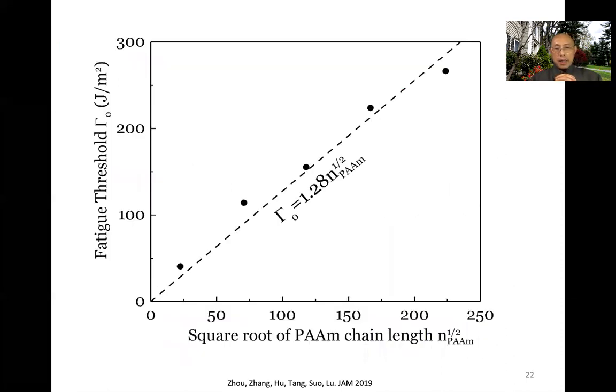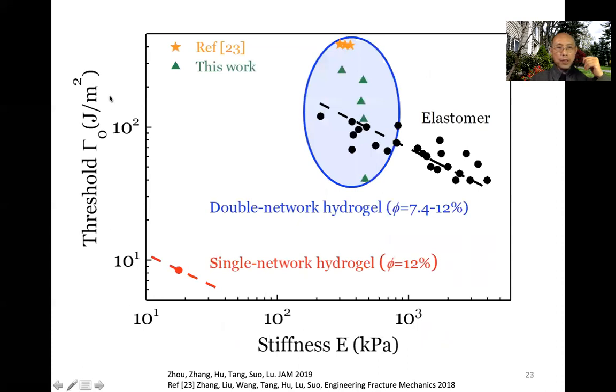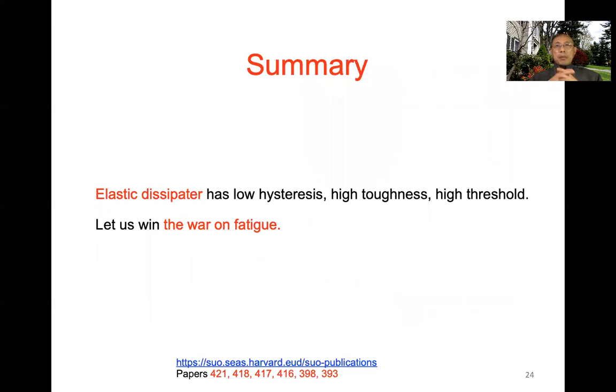So here is our experimental data of fatigue threshold as a function of the number of monomers per chain. You can see as the number of monomers increases, our fatigue threshold does increase all the way to several hundred joule per meter squared. Here is our data of threshold plotted against stiffness. All the traditional hydrogel is somewhere here, not very stiff and not very fatigue resistant. However, if you make this double network, you push the material all the way to elastomer level, and still have 80 to 90% water. That's great. Now, let me summarize the talk today.